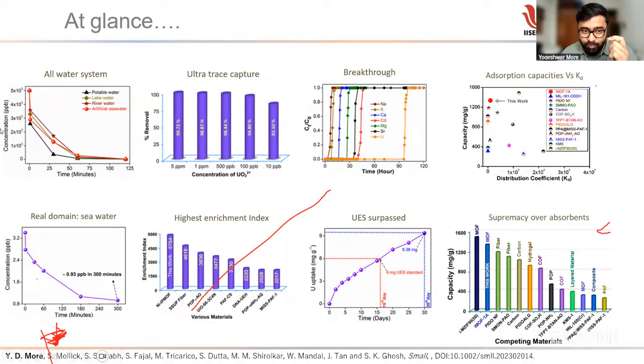In that order, what we did, we had a 5 ppm solution first, then 1 ppm, then 500 ppb. Now we are going in the parts per billion range, then 100 ppb, then 10 ppb. And then we did the uranium exchange for different concentration solutions. We can see that the higher the concentration of uranium, the higher the amount of uranium we extract from the MOF, because the MOF has a high capacity. But when the concentration goes very low, like 10 ppb, the interaction sites barely interact. So what we see, 83% of uranium is recovered, because the probability of interaction in the higher concentration is always high as compared to the probability of interaction in the lower concentration.